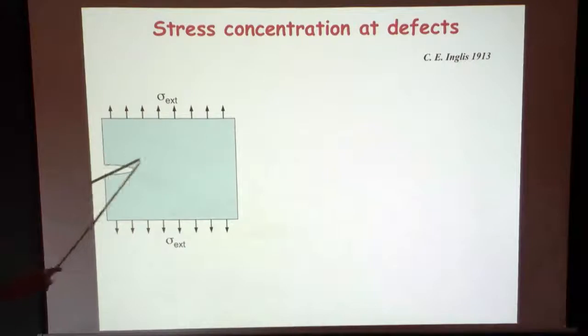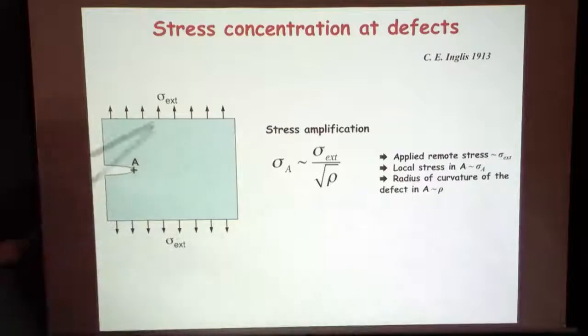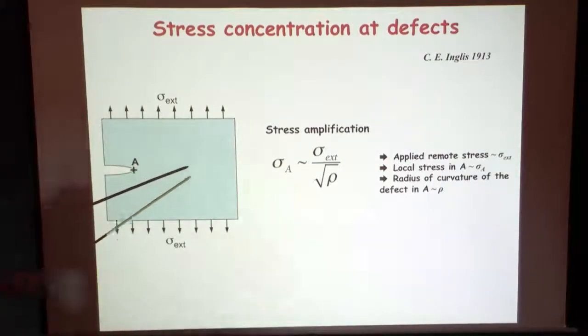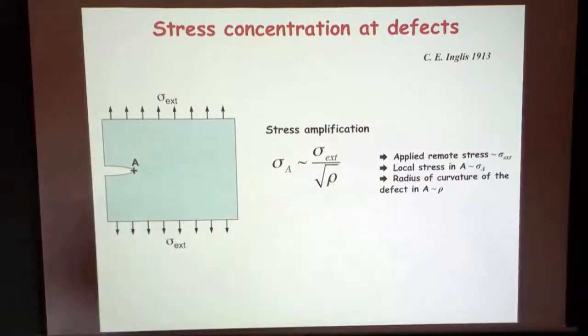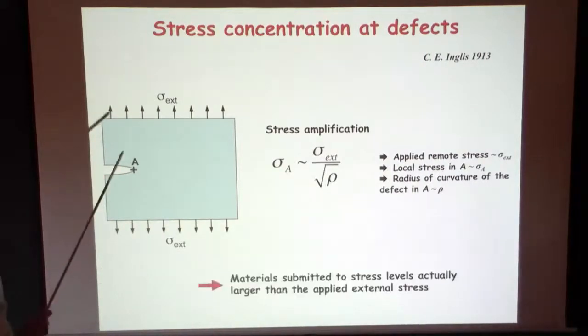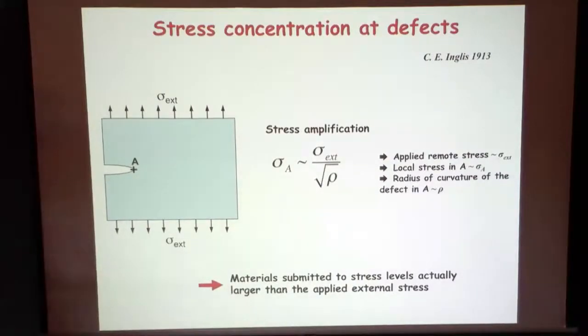So you introduce this kind of elliptical cavity in your solid, and then since you have an elastic material, you can calculate the stress field in this system as you apply a tensile stress on the side of your sample, and show that you have stress concentration, stress amplification, and the amplification factor is 1 over the square root of the local radius of curvature at point A. So you clearly see that the actual stress that the material will undergo is much higher than the stress you apply on the side, and you start to understand why the strength of material is actually lower than the theoretical strength.